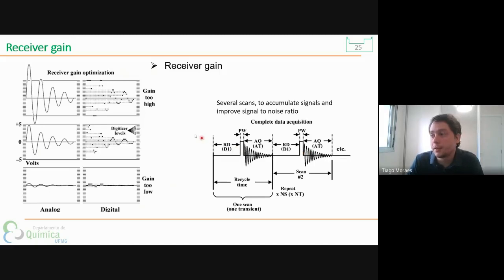There are other parameters that we need to optimize in our spectrometer, like the receiver gain. As you can see here, if our sensor is not in the optimal conditions, you can have some distortions in your signal. For example, if your sensor is in this condition, the gain is too high, so you have some distortions. Also, if the gain is too low, it's not good. You need to optimize this parameter. For different pulse sequences, you need to optimize different parameters of the pulse sequences.